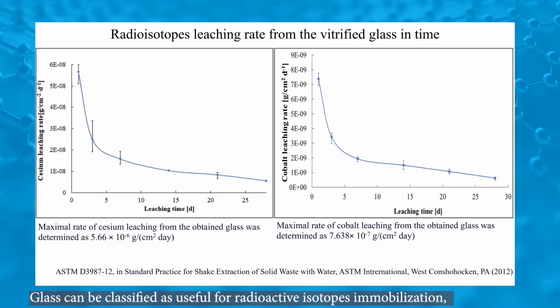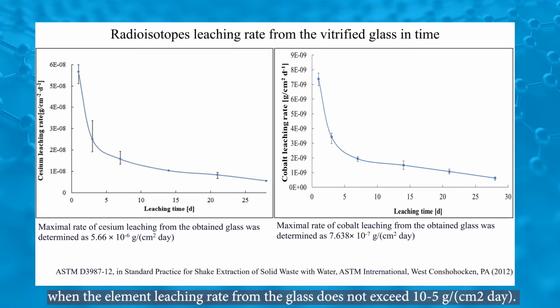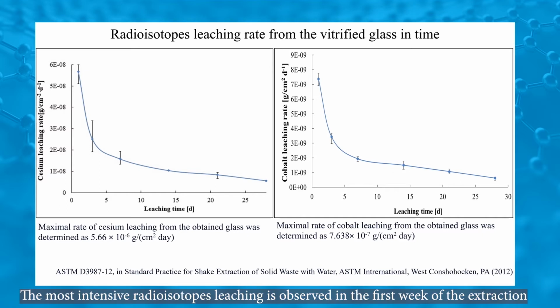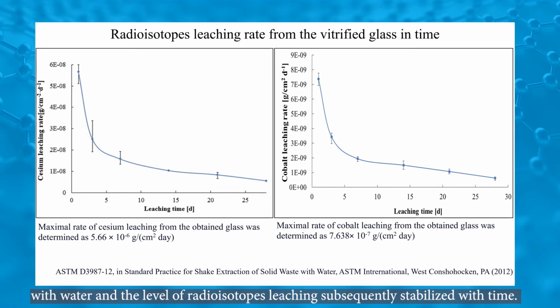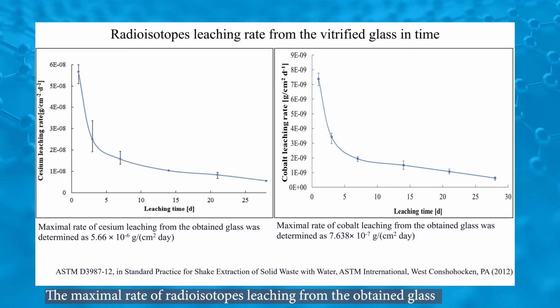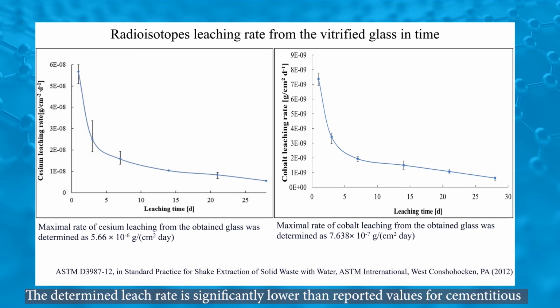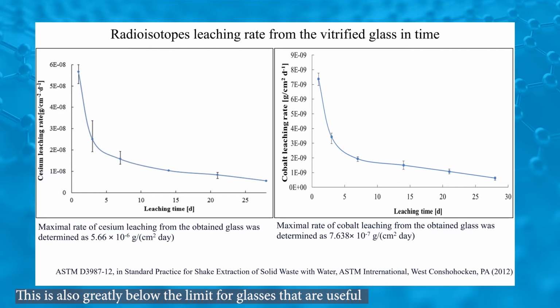Glass can be classified as useful for radioactive isotope immobilization when the element leaching rate from the glass does not exceed 10^-5 grams per square centimeter per day. The most intensive radioisotope leaching is observed in the first week of the extraction with water, and the level of the radioisotope leaching subsequently stabilizes with time. The maximal rate of radioisotope leaching from the obtained glass confirmed the stable binding of cesium in the vitrified material. The determined leach rate is significantly lower than reported values for cementitious and cement-bentonite materials, which are used for radioisotope immobilization. This is also greatly below the limit for glasses that are useful for radioactive isotope immobilization.